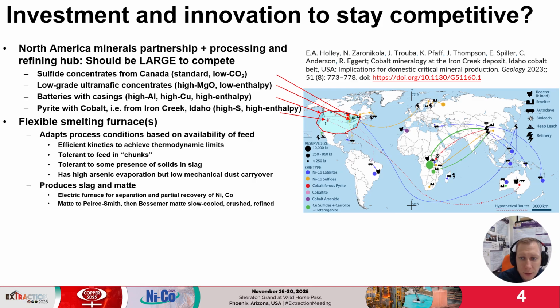Also, from reading the Vale report, I can see that arsenic is a growing problem. Similarly to copper operations, arsenic can evaporate before distributing between slag and matte, but if the mechanical dust carryover is high, the recondensed arsenic will be recycled together with nickel-containing dust back into the furnace, accumulating in the process. The preferred smelting process is the one with a low volume of mechanical dust carryover, because a small quantity of dust is easier to process via leaching, thus bleeding arsenic from the flowsheet and preventing high partitioning into matte. The main product of smelting will still be slag and matte, similar to the current Inco flash smelter. Thus, the existing infrastructure for matte converting and refining can be used.